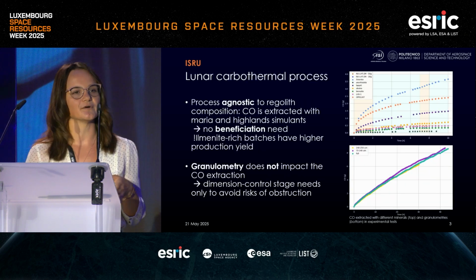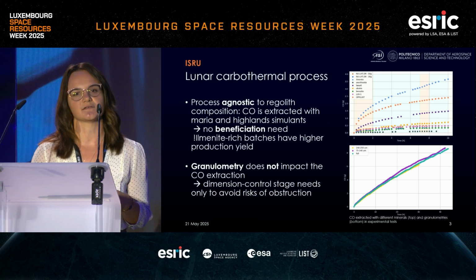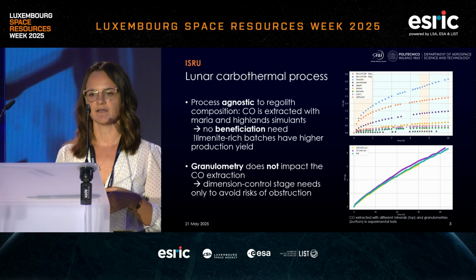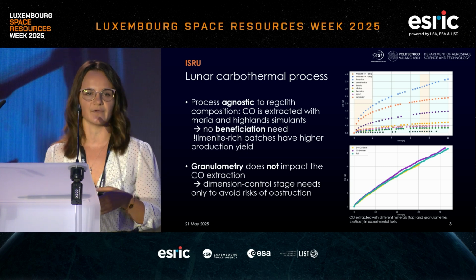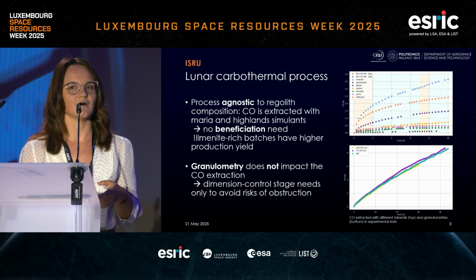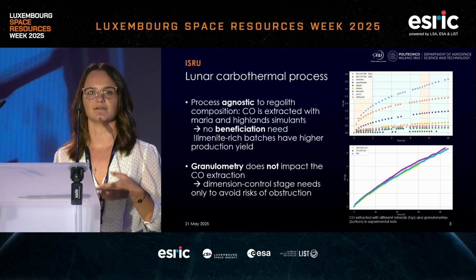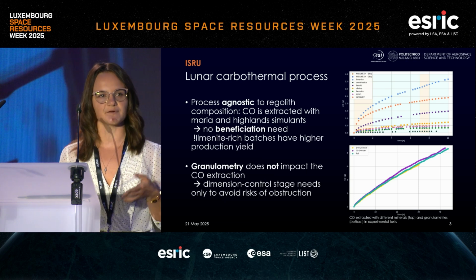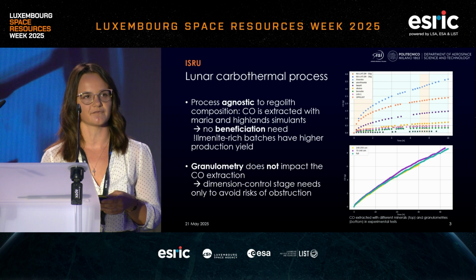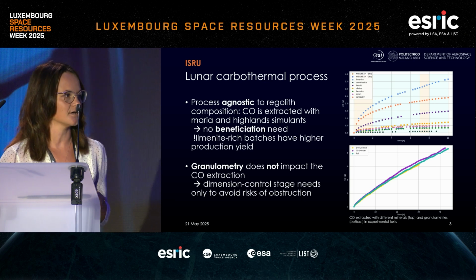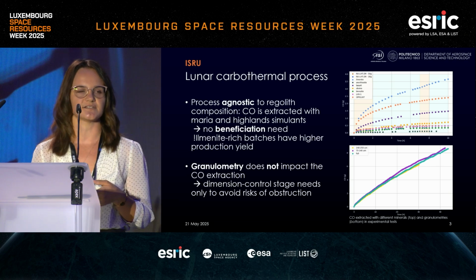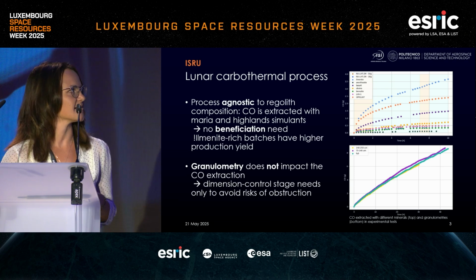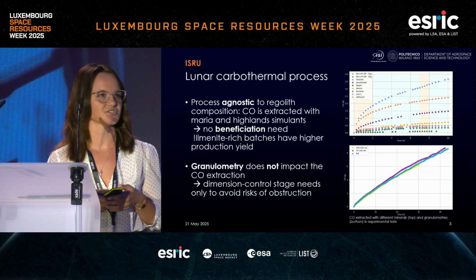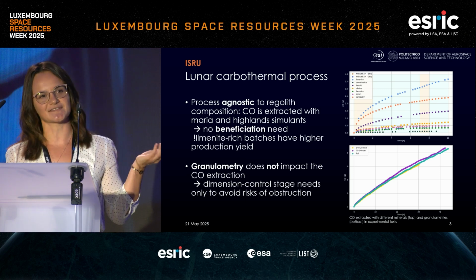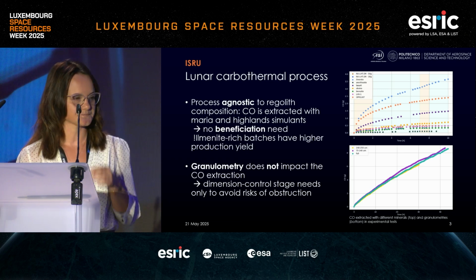And so with regard to the carbothermal plant, we actually won't need so many different processing stages for the regolith, because from the experimental results we have been getting in recent months, the process is quite agnostic with respect to regolith composition, meaning that, for demonstration purposes at least, we are able to extract oxygen in the form of carbon monoxide no matter what the composition. Obviously, if we are working with batches richer in iron oxide, the oxygen extraction yield is much higher, but we are able to extract some CO no matter what the composition. So we won't need a beneficiation stage in our plant.